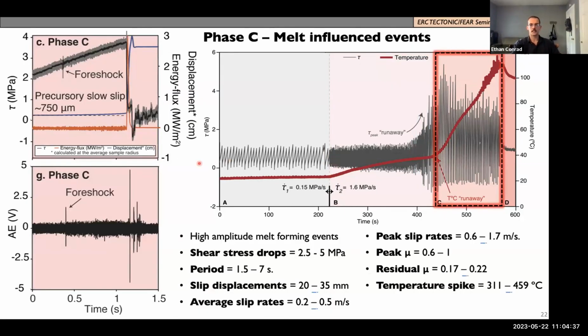And we enter phase C, and like I said, we mark phase C at the inflection in this curve here, where we have this change in the shear stress. It's sort of between the change. You see there's some larger events here, but really once you've established these larger events, and the temperature has reached a new kind of trend, it's increasing linearly now from here.